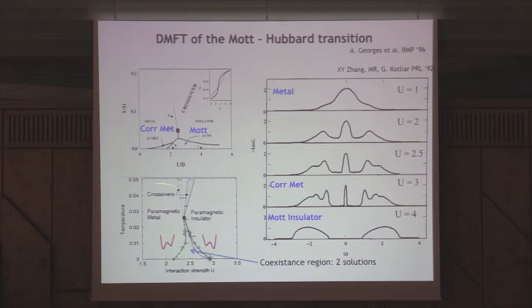So if you put that in a phase diagram, these calculations correspond to T equal to 0. This is interaction in units of the bandwidth. And what I was mentioning before is that at low u, you have a paramagnetic metal. In cranking up u, you destroy it at that value, which we call Uc2. And beyond that, you have an insulator. And when you go back from the insulator, lower in u, you find this region of coexistence, and here you destroy your insulator.